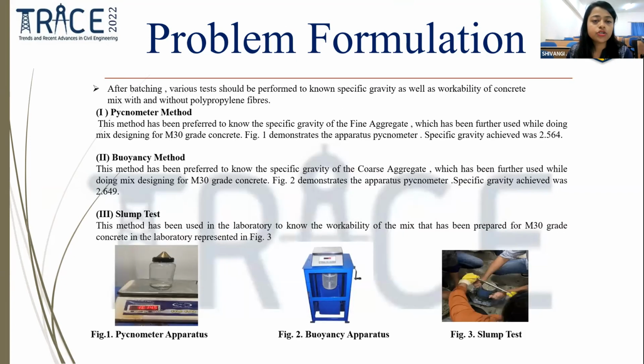After batching, various tests were performed to know the specific gravity as well as workability of the concrete mix with and without polypropylene fiber. We have used the pycnometer method. In this method, we determine the specific gravity of fine aggregate, which is further used while doing the mix design of M30 grade concrete. Figure 1 demonstrates the apparatus, the pycnometer, and the specific gravity which we have achieved is 2.564.